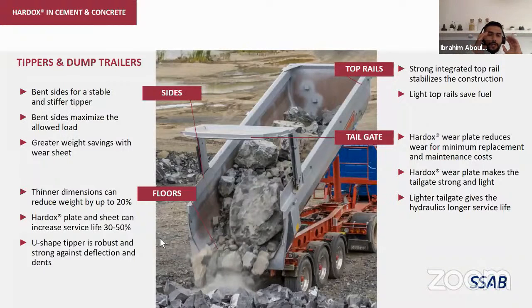Then, so we finished the excavator and loaders buckets, the dump trucks. Now we go to the tippers. Just briefly, in tippers, I really like this segment because there is a lot of improvements that can be done when upgrading from the mild steel tippers to the Hardox tippers. The idea is that in the sides, we avoid using the stiffeners, and for that, we just use bends to increase the stiffness so that you don't lose the stiffness of the tipper. The shape allows to carry bigger rocks, and you have a lot of wear savings.